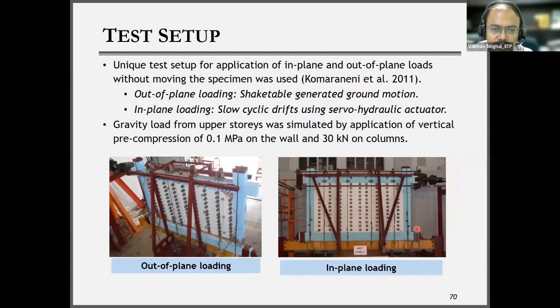In this case, we have used a very unique test setup, where the specimens are subjected to a sequence of in-plane and out-of-plane loads. The objective here was to see the performance of a masonry wall when it is damaged. And especially if any damaged wall is subjected to out-of-plane shaking, it is more vulnerable to a complete failure. So that is what the objective was: we will put some damage to the wall and then do a shake table test and see how it will perform.